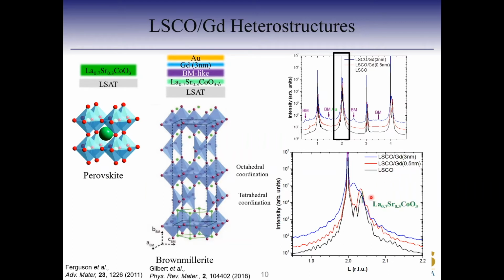So as you start with an as-grown material, you get the 002 crystal Bragg peak. And then as you start to add gadolinium in the material, let's say half, you start to create oxygen vacancies. At that stage, because you're creating oxygen vacancies, your lattice would expand due to the repulsion between cations, and so the peak actually shifts to a lower theta. And then as you increase the thickness further, you actually move away from perovskite and start to get this brownmillerite-like phase. So this is actually a peak which belongs to the brownmillerite structure.